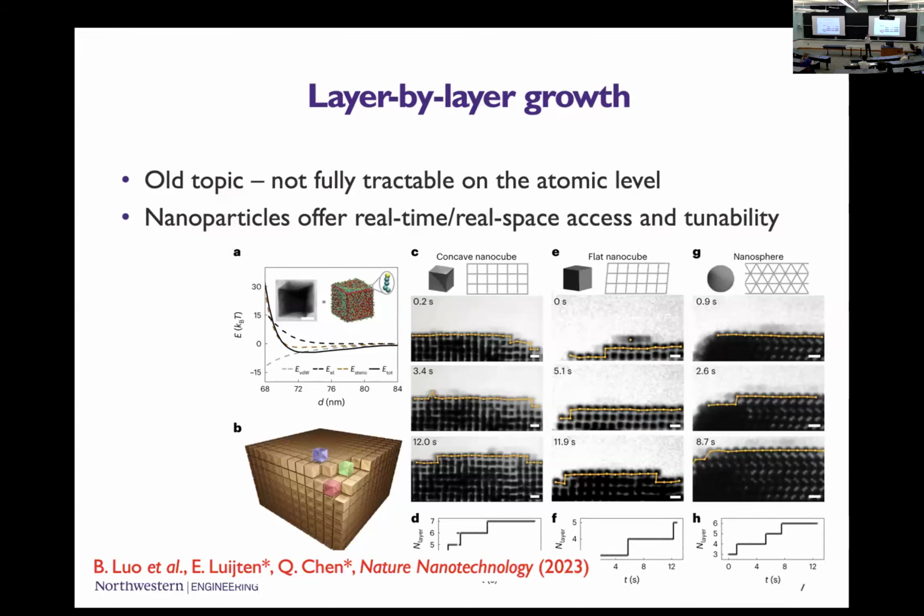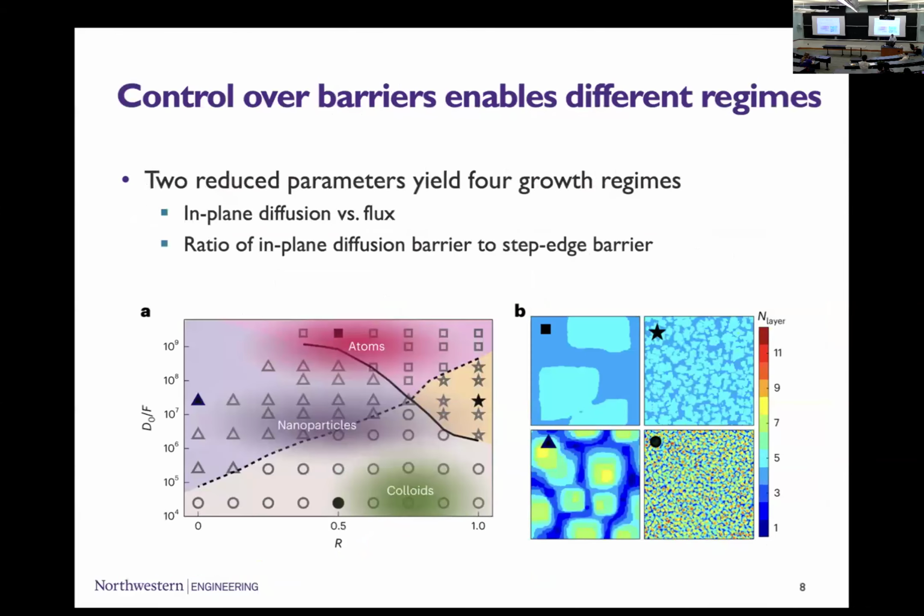So these are the still images here on this slide from the observations, but you can see that we can actually track particles sliding back and forth, and even for nanoparticles, and even with all this sophisticated technology, that's pushing the limits of what we can do, because of the resolution of the TEM cameras, the latest generation. The company is called Gatan, it's like K2 and K3 cameras, very expensive. They still have like millisecond resolution at best. And so if you actually check the rate at which particles are moving when they have this size, then you're really pushing it. If you see milliseconds, then the particle might have moved quite a bit before you take your next image, but still, you can see what's happening. We can characterize the growth of the individual layers. And so that's very informative.